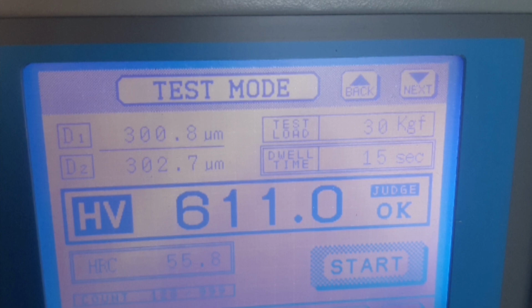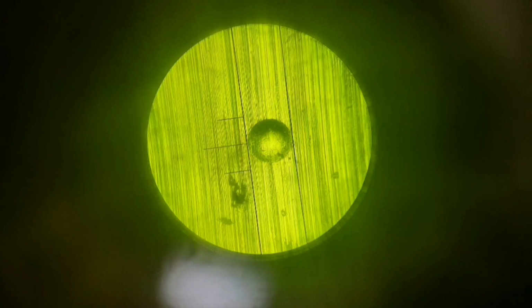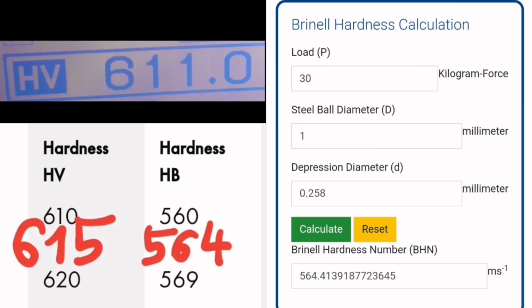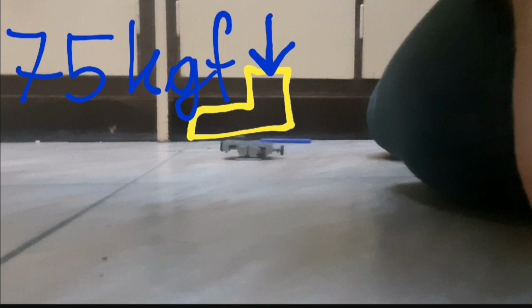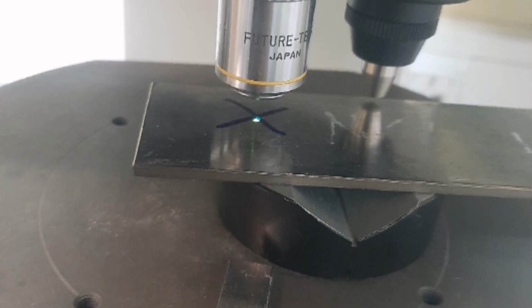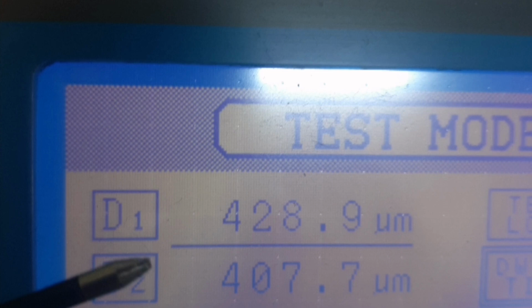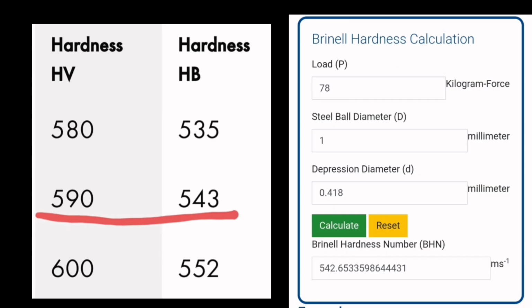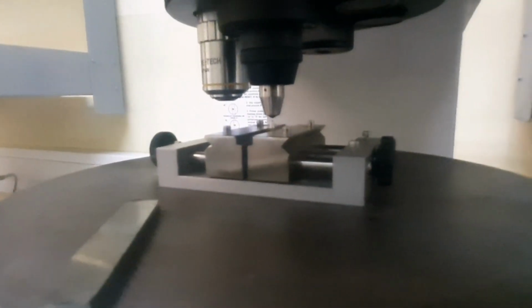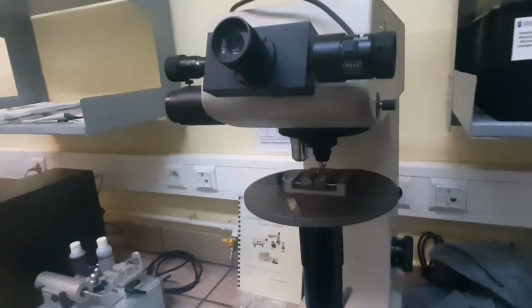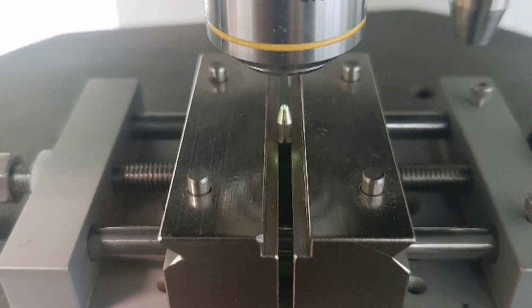Vickers hardness on top is 611 Vickers. The Brinell hardness on the bottom is 564 Brinell, which translates to 615 Vickers. So 615 versus 611, very close. I will now stand on the vise and press the ball into the steel with the force of my weight. The measured diameter is around 400 micrometers, and the hardness in Brinell is around 540 Brinell, which translates to 590 in Vickers. The value is pretty close to the 611 measured with the laboratory equipment before. You need to remember that the steel is not uniform, the hardness value varies.